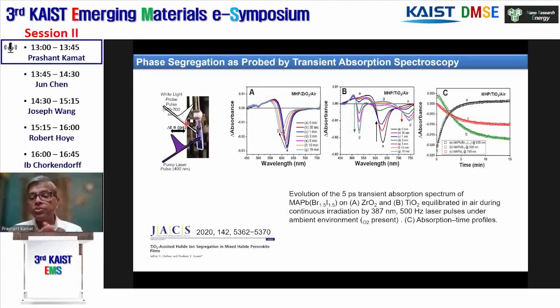And you can see here how the emission grows in this case. And then what we did was a transient absorption, and we recorded absorption 5 picoseconds after the laser pulse while it is continuously irradiating with the pulse laser. And here you can see in the case of TiO2 air, the mixed halide peak starts going down, and the bromide bleach and the iodide bleach are increasing. These are essentially the excited state of bromide and iodide phases. And as these iodide-rich and bromide-rich regions are generated, they also get excited. And as a result, we see the bleach in this case. And if you do it on zirconium oxide, we don't see anything close to it, but a small decrease. And this decrease could be due to expulsion of iodine from the surface in the laser excitation, because you can see the shift in the bleach peak in this case. In any case, we can follow this on TiO2 and get the kinetics of this segregation.